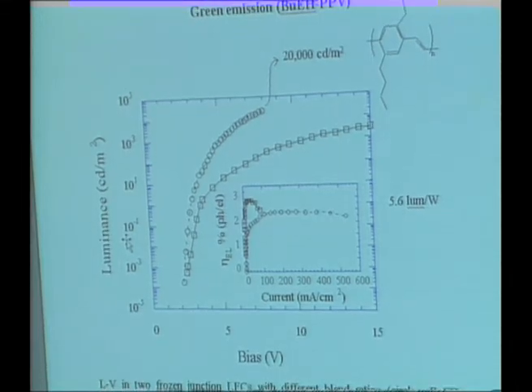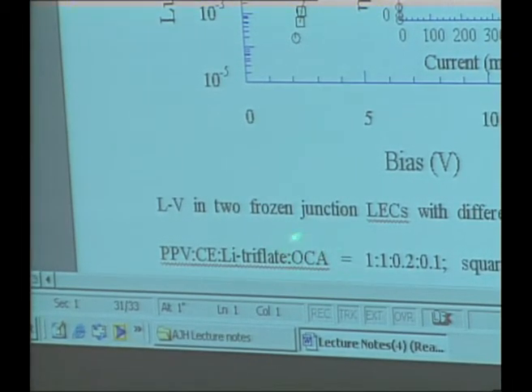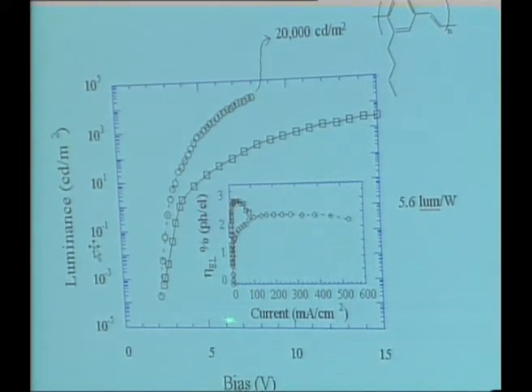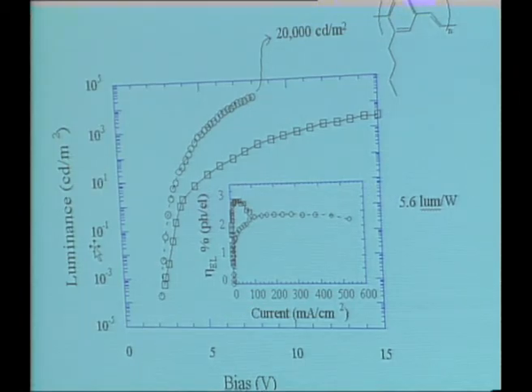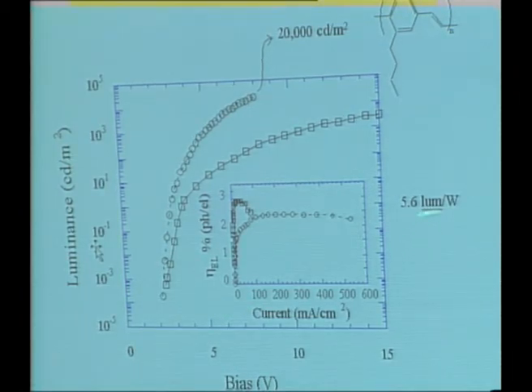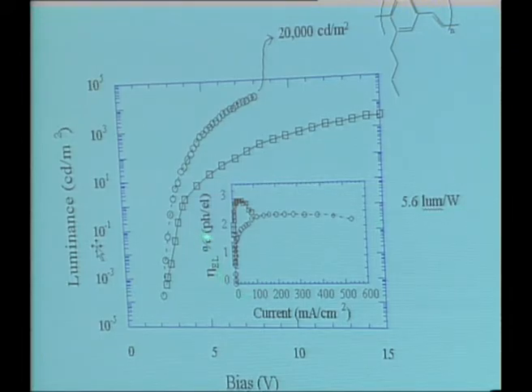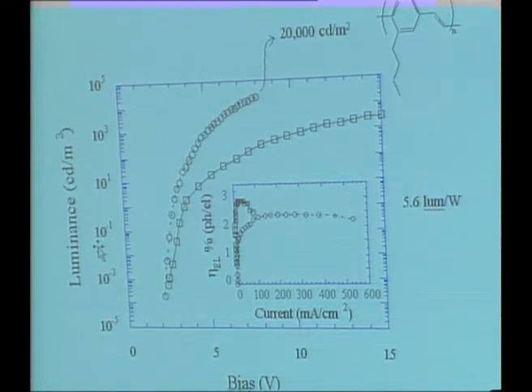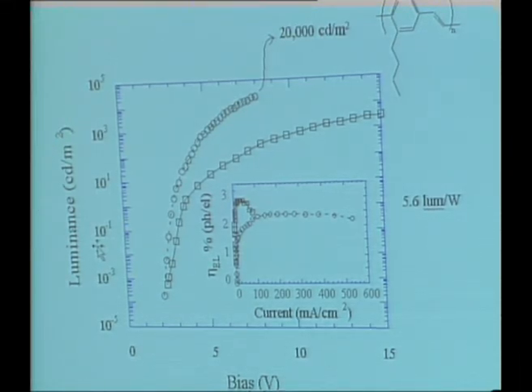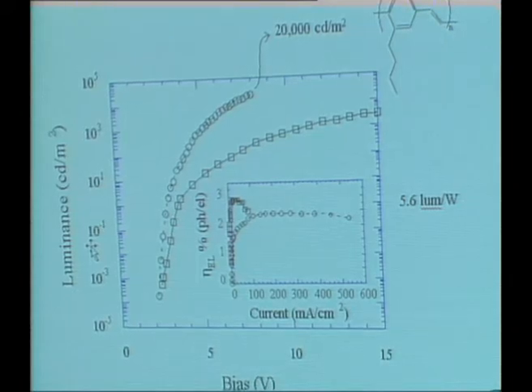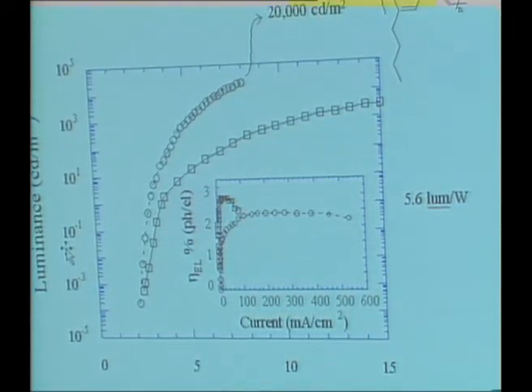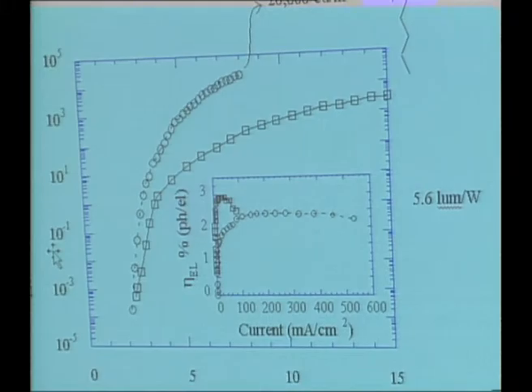This is, again, using this surfactant bifunctional molecule. You can get 20,000 candelas per square meter here at 6 volts. That's pretty damned impressive. And the 5.6 lumens per watt, quantum efficiencies, which are high. So the point here is to leave you with the correct impression that one can get high performance devices out of this.